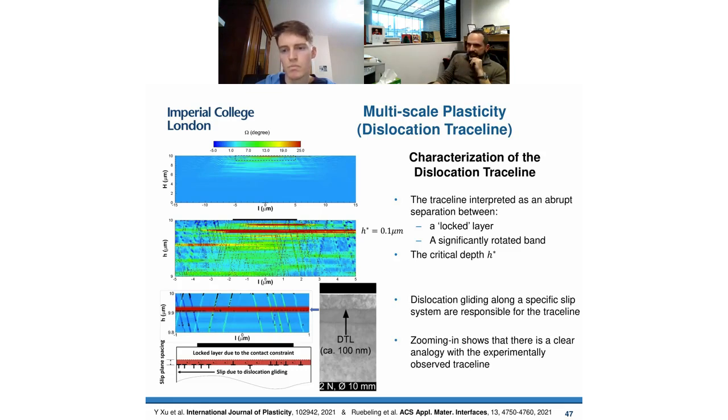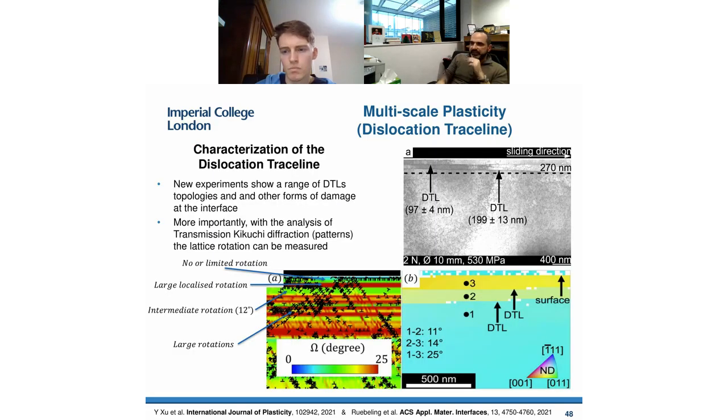And again, the last slide on this I would like to show is that this can also be used to explain what happens at larger loads. So if you apply larger loads and you do the same, obviously the material doesn't just form one line. It could actually form more than one line, and it can also start deforming, creating new grain structures, which is what Christian saw in other experiments he did. But this is exactly what happened also in our simulation.